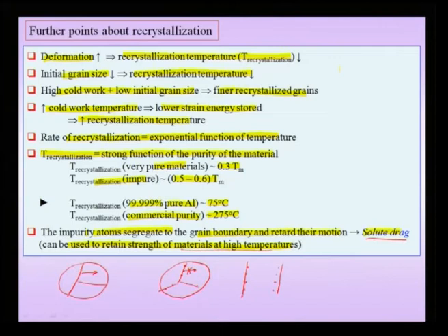So, we have to worry about the amount of deformation we put in, the purity of the material. The lesser the purity, the higher will be the recrystallization temperature, as nicely demonstrated for the case of aluminum, where the recrystallization temperature can drastically increase if you take an impure material. Further, we also have to worry about the grain size of the starting material which was deformed.